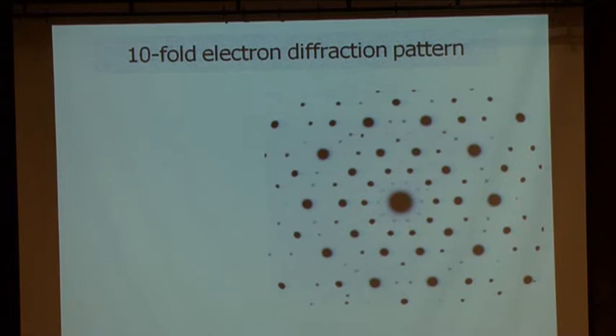Convergent beam electron diffraction means that you converge your beam onto a point, very small point, as small as you can, and take a diffraction from that area. And if that area will hit just one periodic crystal, then you'll see one periodic diffraction pattern. And you move to the next one, you see another one rotated. That didn't happen. There were no twins there. And I knew in day one that there were no twins there. Why do I mention that? Because my main opponent didn't believe in my results and claimed that there are twins in these crystals, and he did that quite a few years, 16 years after the discovery.